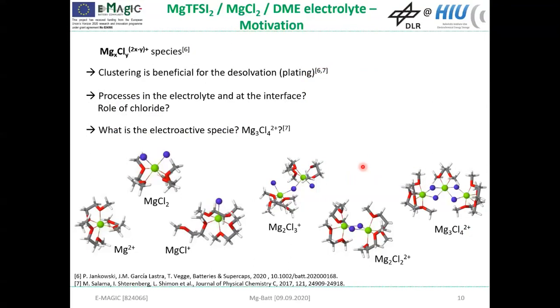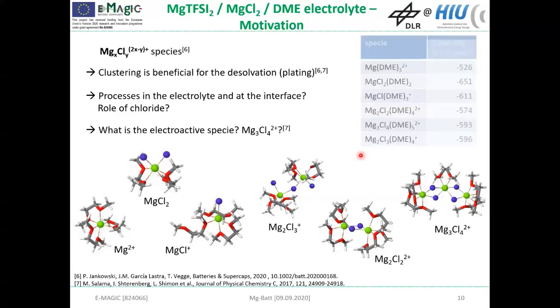And with our continuum model, we hope to get more insights into the role of the chloride in the electrolyte and at the interface. So, for example, one question is, which of all those possible species is the main electroactive species? As you already heard earlier, our colleagues from DTU also had a closer look at all those different magnesium chloride clusters, and they determined the free energy for each of them. And these results from the DFT calculation are the basis for us to have a closer look at the thermodynamic equilibrium between those clusters and the bulk electrolyte.